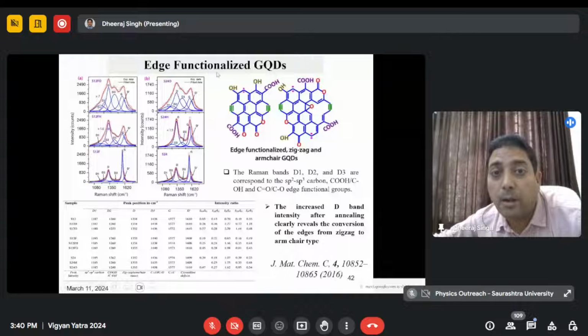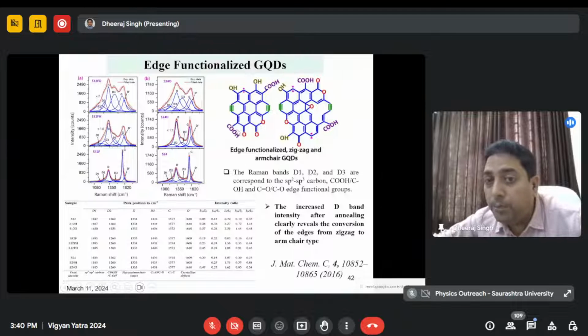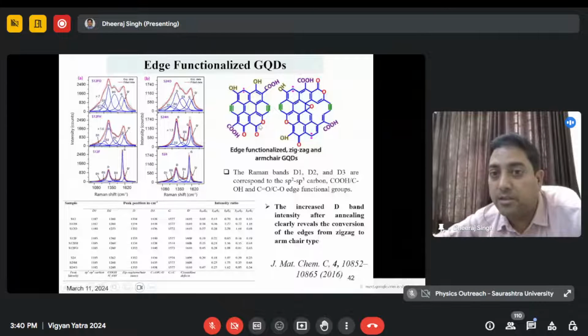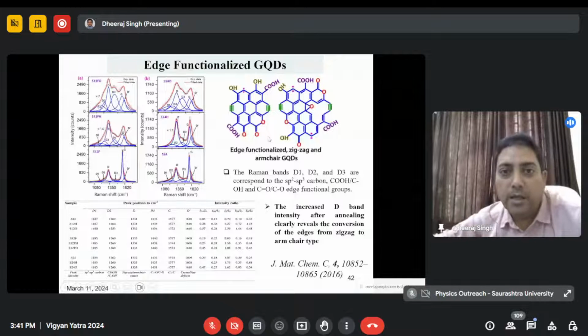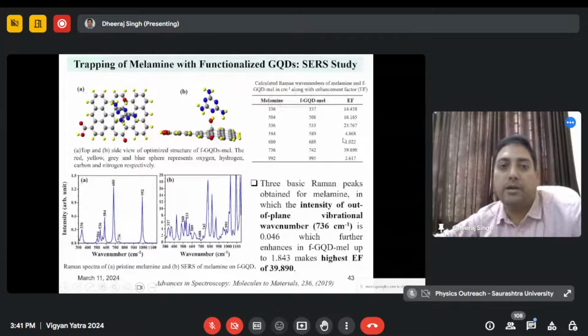Furthermore, we can also show what happens with functionalized graphene quantum dots. Suppose here we have functionalized the carboxylate group, OH group, OH group, COH group. The size of this molecule is increasing, and also in zigzag and armchair forms, because there are three types of quantum dot: armchair, zigzag, and chiral structure. So these types of structure can also be characterized by the functionalization group, like D1, D2, D3. D3 means this system can be characterized in terms of the COH group, C double bond O group. So whatever functionalization you have used in your carbon-based material can be clearly identified by Raman spectroscopy. Further, the ratio of the I D and G band intensity variation you can identify.